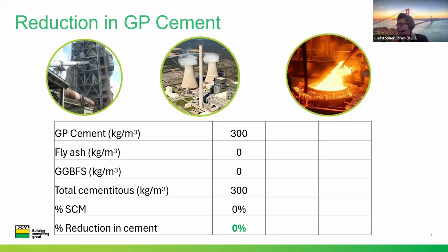The other thing we need to consider is the reduction in GP cement which results from using these products. Let's look at this mix, which contains 300 kilograms of GP cement per cubic meter. We can use fly ash to reduce the cement content, but fly ash is not as potent as GP cement. So for every 1 kilogram of GP we take out, we have to add 2 kilograms of fly ash. So in this fly ash mix, we reduced the GP content by 50 kilograms and replaced it with 100 kilograms of fly ash.